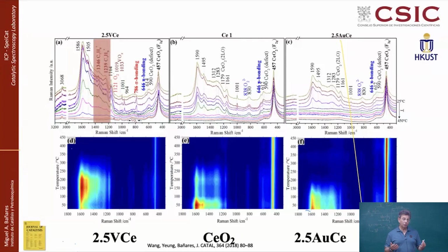And these have more tendency of forming polyolefinic hydrocarbons, evolution more towards carbocations, and things that in the end end up building up more carbon deposits that accumulate on the surface. And of course, these are more refractory. They take longer to be burnt away, and actually you need higher temperatures. So vanadia ceria is leading to this carbenium that make more complex structure on the surface, require a major effort for combustion, and then it is not a very good total oxidation catalyst, which doesn't happen on ceria and doesn't happen on gold ceria. And in the case of gold ceria, you even get rid of carbon deposits much sooner than on the other.